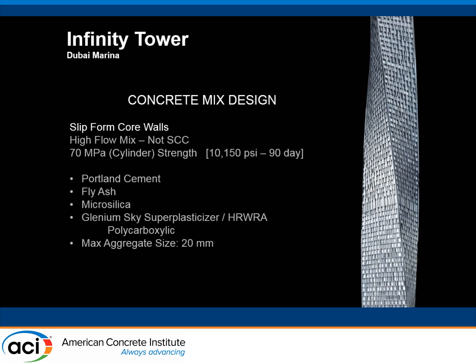But because they were using slip form, it wasn't a self-consolidating mix because you need a certain amount of early age strength to do the slip forming. But it was a high flow mix, 70 MPa cylinder strength, about 10,000 PSI. Again, this bi-mix, which has fly ash and Portland cement together, microsilica and a superplasticizer, no viscosity modifier in this case. And we bumped up the max aggregate size to 20 millimeters.